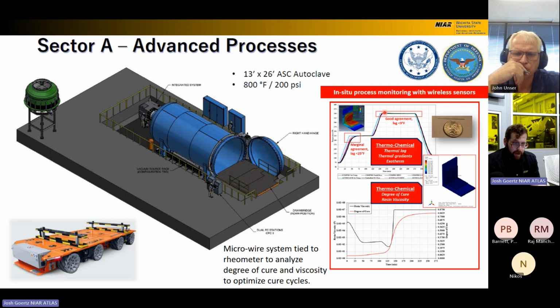So your recommended cure cycle is going to be kind of conservative, based on, they don't necessarily know how thick your final laminate is going to be. They don't know what kind of tool geometry it's going to be on. And this will let you reduce your dwell times and increase your heating rates to the shortest extent possible, so you can fully optimize your traditional thermoset cure cycle.